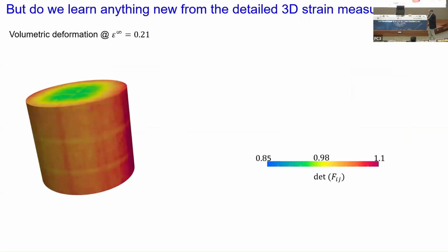So now let's see something which no two-dimensional measurement would have ever told you anything about. One of the things you can look at, because we've got full 3D measurements, is the volumetric deformations point by point inside the specimen, not the change in volume of the whole specimen, but for each material point inside the specimen, how is its volume changing? So I'm now plotting what we call the determinant of the deformation gradient. If the determinant is 1.1, that means I'm getting a 10% increase in volume. If the determinant is 0.85, it means I'm getting a 15% reduction in the volume. Okay, so that's what we are seeing here. So now let's look at this movie for a minute, and then we'll discuss what physics it seems to be telling us.